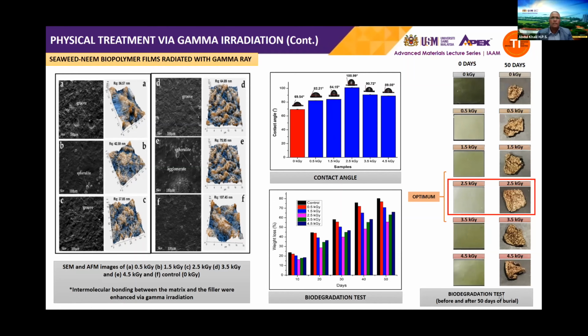For the biodegradation test, the percentage of weight loss increased with the number of days up to 50 days. This study proved that the optimum dose used to enhance the properties of the seaweed neem biopolymer is 2.5 kilogray. When doses increase beyond 3.5 kilogray, degradation occurs, thus lowering the properties.